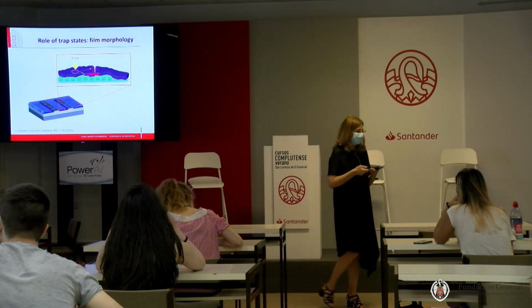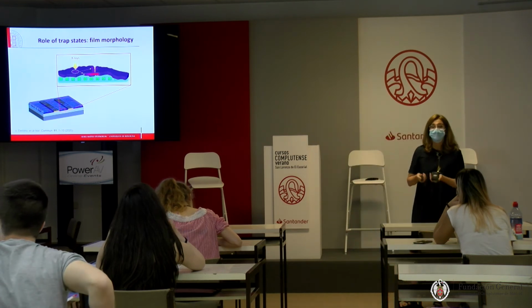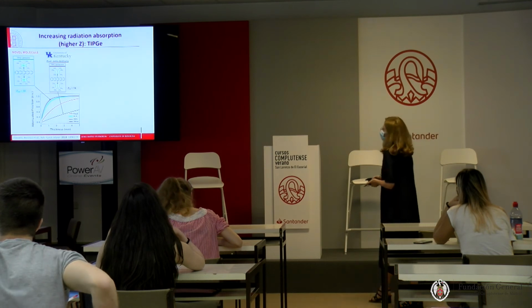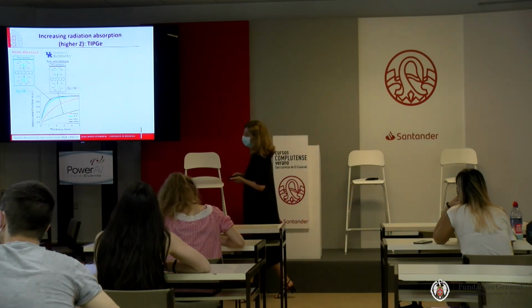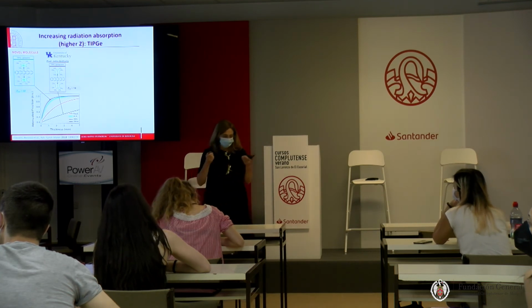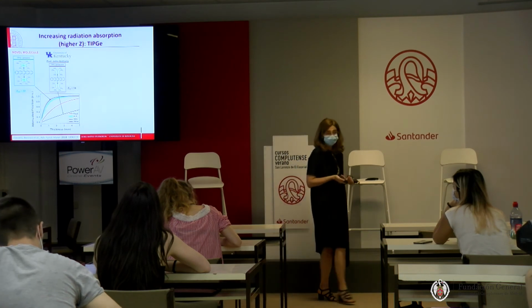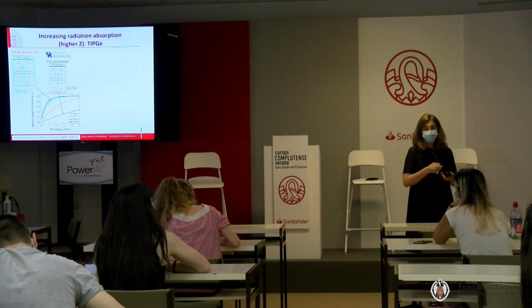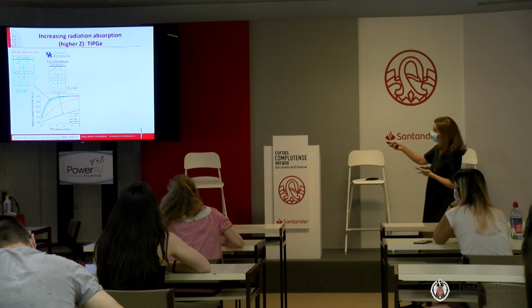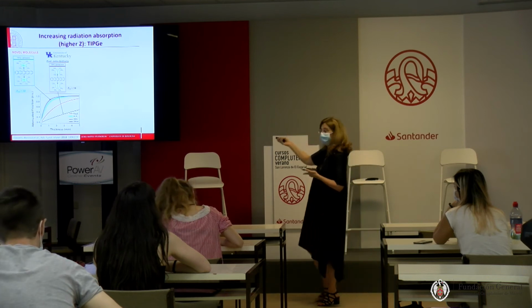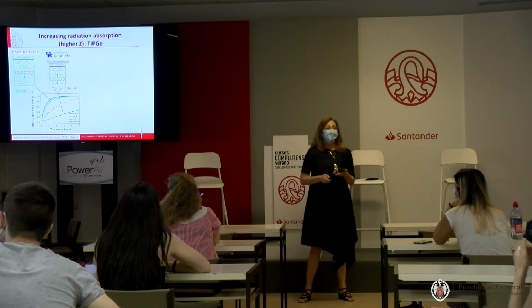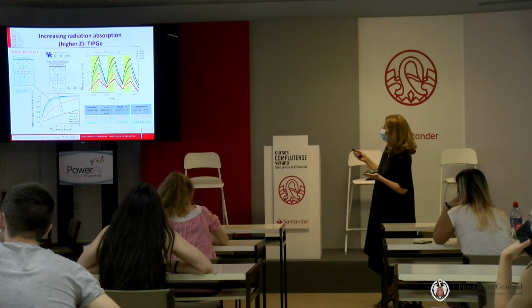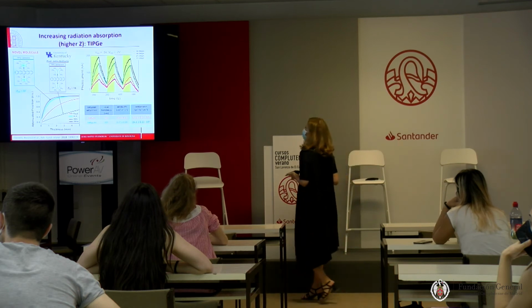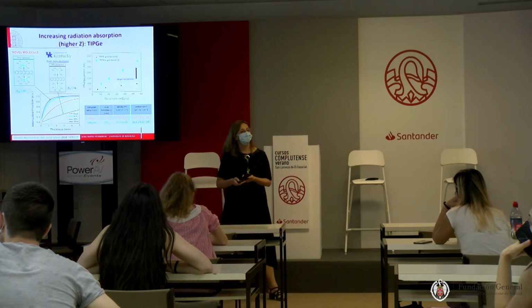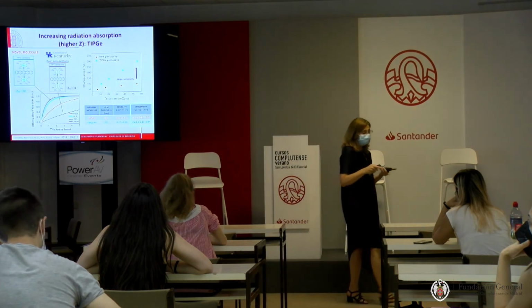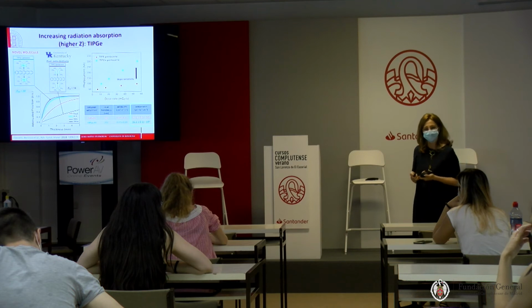So that is just to say that we can play around with many parameters thanks to these functional materials to impart the properties we believe are needed for the application of the X-rays. One last comment is about the atomic number to increase the radiation absorption. How do you increase the radiation absorption? By increasing Z. We have organic molecules, as I said, carbon, hydrogen, and 2 silicon atoms. If we simply change 2 silicon atoms with 2 germanium atoms, the atomic number increases, and the molecule is still working as a good semiconductor, still responding well to X-rays, and the sensitivity is increasing. In this case, we're not working on the defects, but we are working on the absorption coefficient. Okay?